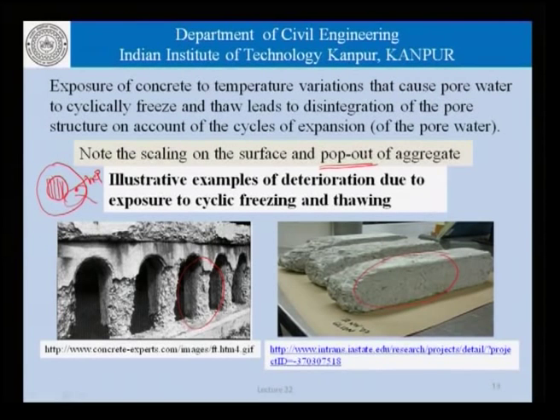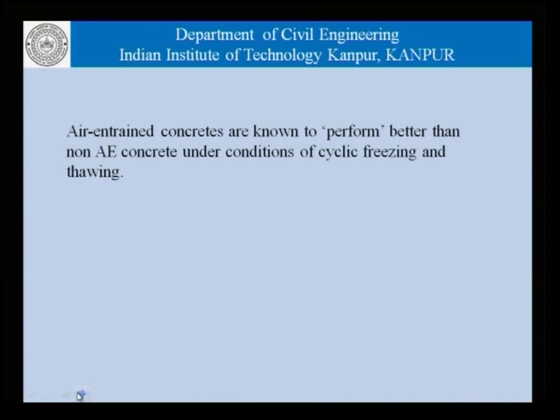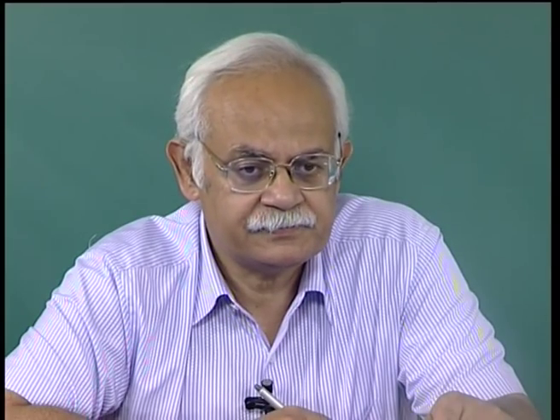So, one of the things that happens as far as freezing and thawing of concrete is concerned is scaling, pop out and a general disintegration of the surface layers. Now, air entrained concretes are known to perform better than non-air entrained concretes under conditions of cyclic freezing and thawing, and this is something we have talked about before, in proportioning of concrete mixes and even in the earlier discussion on durability.